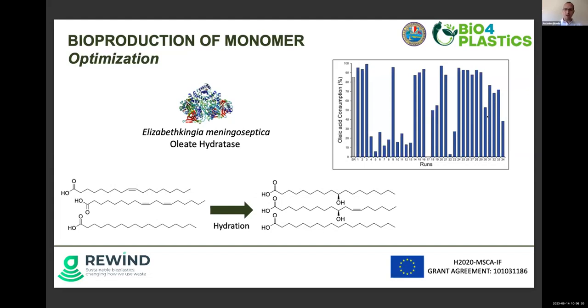As you can see in the graph on the upper right, the standard reaction, SR in gray, already had a very good oleic acid consumption, approximately 85%. But through this approach of design of experiments and optimization, we were able to reach up to 98% of oleic acid consumption. Oleic acid is one of the main components of free fatty acids derived from waste cooking oils. So this was one of our main topics to improve this part.